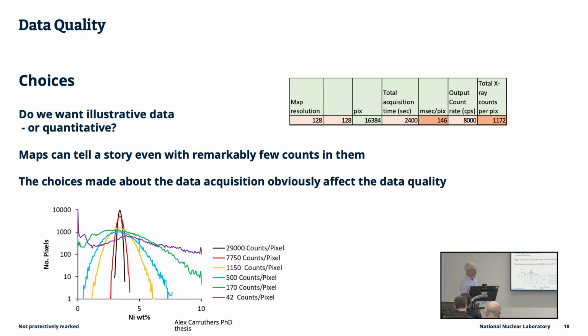So if you start off with a low number of counts per pixel, then the spread in the quantification is enormous, whereas when you increase the dwell time up to something much more, producing a much better spectrum, you narrow the error bars, and the distribution of measurements comes right down. So it just illustrates the importance of spending long enough doing the mapping. But that might mean you get 4 or 5 maps done in a day, which might not feel like a lot of work compared to the number of images you could produce if you were doing dislocation imaging or something.